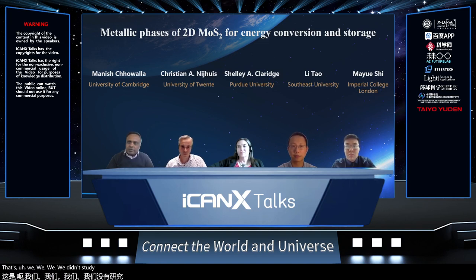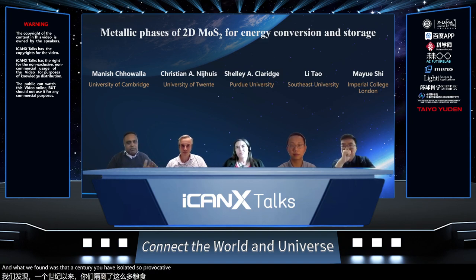We did a study, a few years back now, where we intentionally introduced sulfur vacancies using a helium ion beam. The helium ion beam is very good at gently introducing sulfur vacancies, knocking off the sulfur atoms without destroying the MoS2. If you take something like xenon or argon, it's very big, so sometimes you damage the structure as well as removing the sulfur. But the helium allows you to gently take off the sulfur atoms, and we increase the sulfur vacancy concentration by increasing the dose of the helium ion beam. What we found was that essentially you have isolated sulfur vacancies up to a certain concentration. I can't remember what it is, but say on the order of around 10%. And then you start to create these di-vacancies.